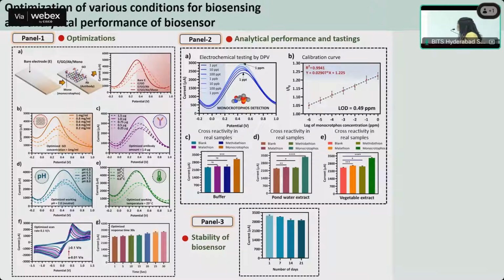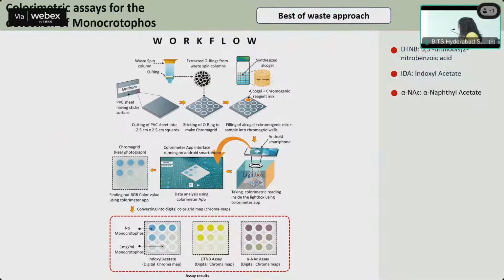Different concentrations in this case with the antibodies gave us an LOD of 0.49 ppm. And the cross-reactivity was also tested in the buffer samples, pond water and vegetable extract. The sensor was stable up to 21 days in this case.